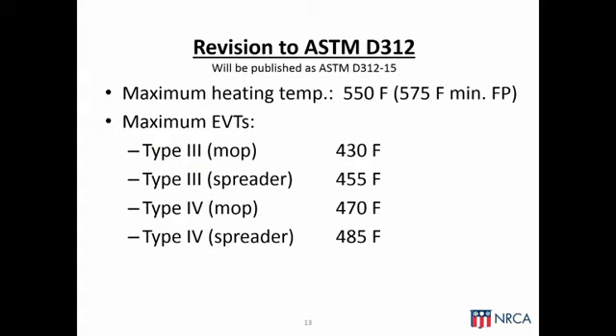EVT value for what we're testing right now or several months ago was about in the 460 to 480 range. The new standard is calling for a 430. In other words, what we're doing is providing a differential between EVT temperatures and that maximum heating temperature.